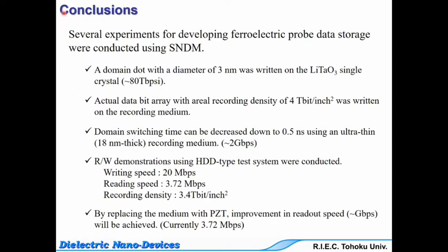In conclusion, several experiments for developing ferroelectric probe data storage were conducted using SNDM, scanning nonlinear dielectric microscopy, and we obtained the following results. At first, a domain dot with a diameter of 3 nanometers was written on lithium tantalate single crystal. The corresponding memory density of the 3 nanometer diameter is 80 terabit per square inch. And an actual data bit array with a recording density of 4 terabit per square inch was written on the recording medium.